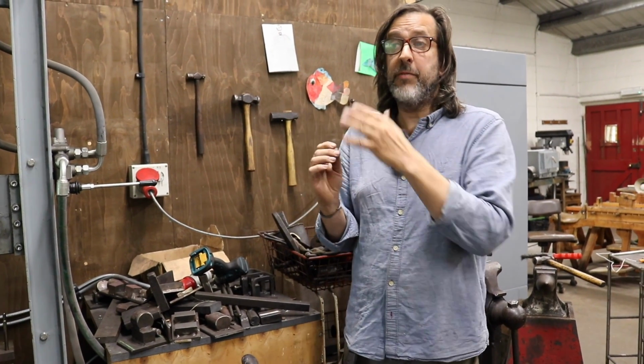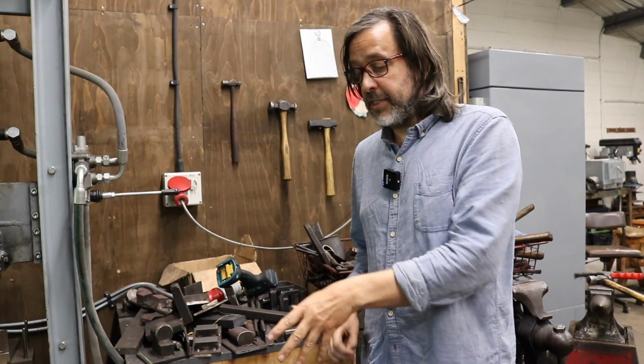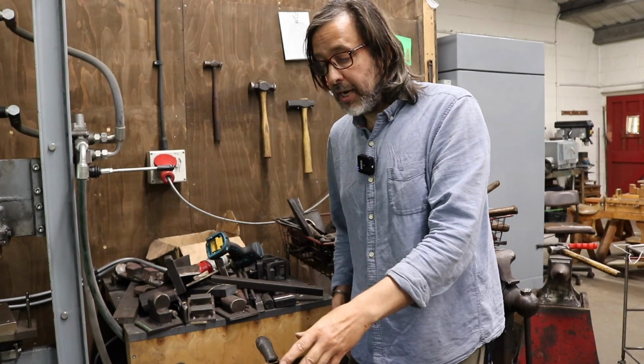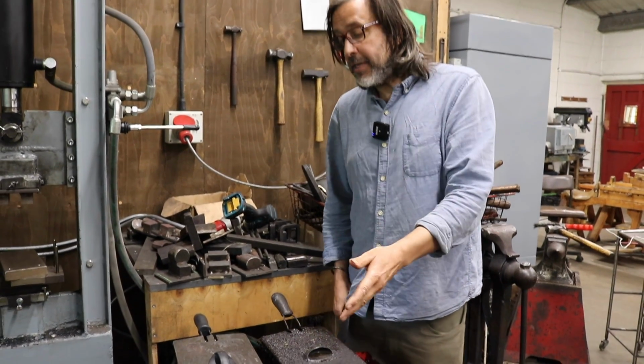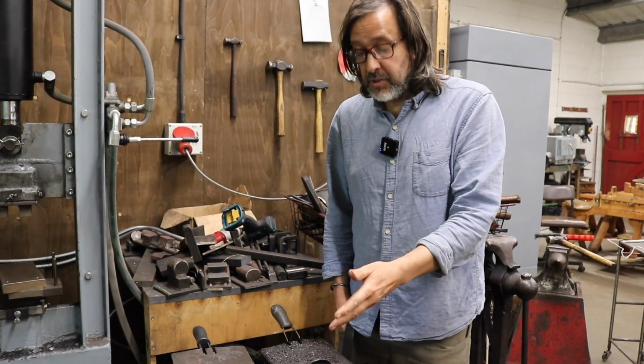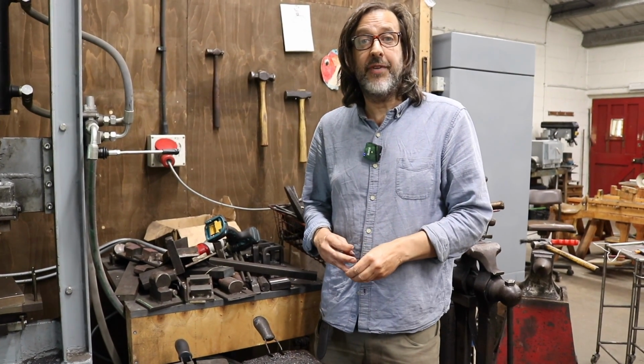And when we've actually ground a blade, I'll show you this edge deflection thing to show you what that looks like. But tempering cuts back some of the hardness of the steel and increases the toughness. It depends on the steel, but 190, 200 degrees centigrade works well for bearing steel, so that's what I'm using.